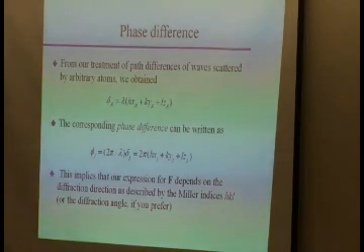Remember, we said we sum over all the atoms. So that means that our vector f, the amplitude of a wave, depends on the diffraction direction as described by HKL, which also would be the diffraction angle if you choose a more common frame of reference. This is what describes the amplitude of your wave.